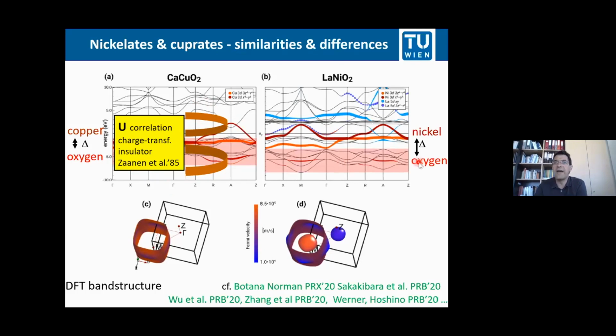For the nickelate, the situation is different. The oxygens are way further down in energy. Therefore, your holes will not go to the oxygen orbitals. But instead, you see here at the gamma point and at the A point, for both niobium and lanthanum nickelates, some pockets, which you also see here in the Fermi surface. So that is the Fermi surface you also know from the cuprates. And then you have the gamma pocket and the A pocket. And the x squared minus y squared Fermi surface sheet is a little bit warped compared to the cuprates because of these pockets. But otherwise, it's very similar, like that kind of Fermi pocket.